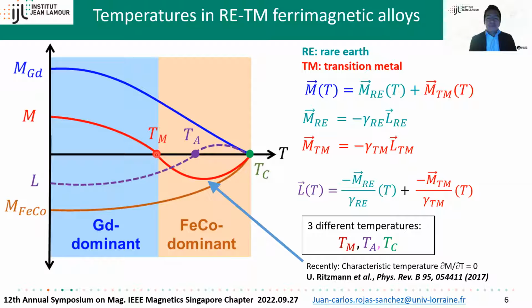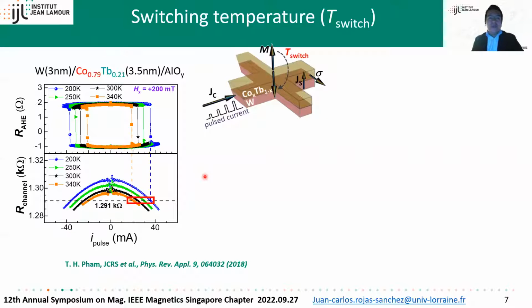That is important, and I will use it almost at the end of my talk: keep in mind that between Tm and Ta, the total magnetization and the total angular momentum are parallel. That explains the signature, the difference between the self-torque and the external spin-orbit torque. Recently, there is a theoretical work reporting a new characteristic temperature where dM/dT equals 0. And indeed, we have reported experimentally in tungsten cobalt terbium also a new characteristic temperature.